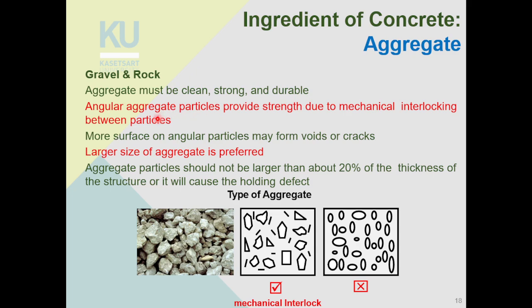And angular aggregates are preferred. Angular aggregate particles are preferred because angular aggregate provides better strength due to mechanical interlocking between the particles. So, for example, these are rocks that we use in concrete. If you have angular aggregates, like in this picture here, the strength could be higher than the aggregate in this picture here. When you have rounded aggregates, when you apply the load, the aggregates will just slide past each other. They're not catching, they're not interlocking. So you get lower strength for more rounded aggregates. But when you have angular aggregates, like in this picture here, the particles are interlocking with each other. You get better load transfer, you get higher strength.